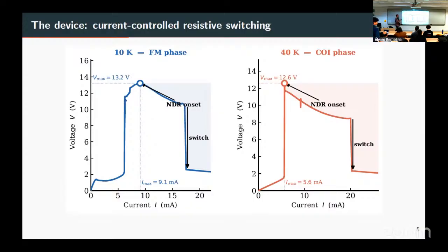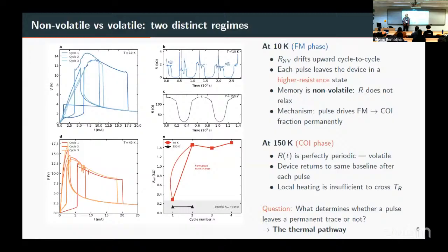Here, because I want to use this as a device, I care about the IV characteristics, so the current and voltage behavior. So here I'm showing you the voltage and current characteristics, and you see that there are also some jumps in the system, and in this particular sample you have a value where the resistance drops. This is completely different from whatever material you remember from your courses, and the key factor is that if you calculate the local resistance here, you have a huge change in the resistance, okay? And this is reproducible, so if you do several cycles, the resistance changes a little bit, but it's more or less the same behavior.